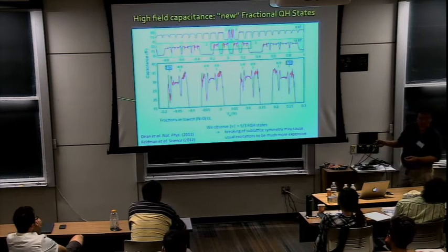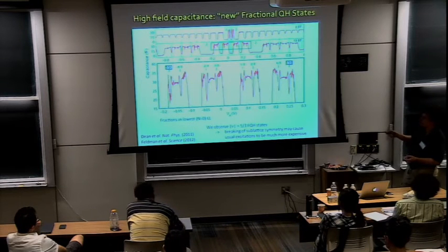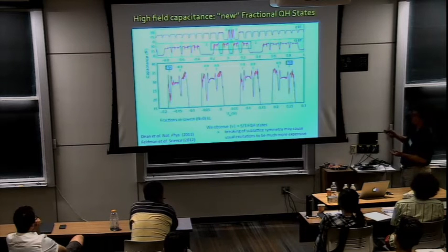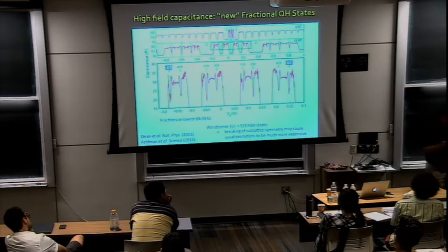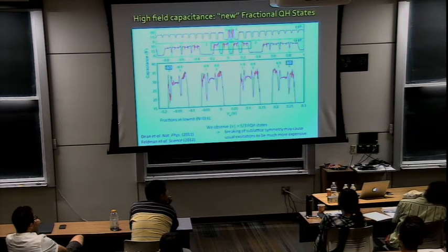These are the 4 Landau levels in the n equals 0 Landau level, okay? You see these fractional states, 1/3, 2/3, 4/3, and 5/3. It turns out that in previous studies of the fractional quantum Hall effect in graphene, people did not see 5/3. And they were initially surprised. They would always see 1/3, 2/3, 4/3, and then 5/3 would be missing. It turns out that theorists believe that the excitations to 5/3 are very cheap because of sublattice symmetry in